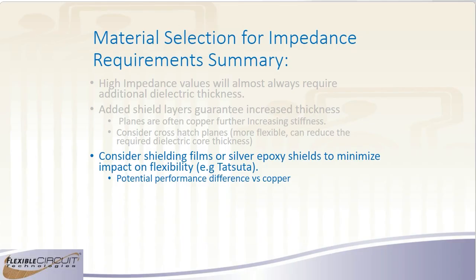And another thing to consider to try and get it more flexible if you do need impedance or isolation is a shielding film. And there's a couple different versions on the market these days. The most common is made by Tatsuta, and it's basically a single laminate that has multiple layers in it that have an anisotropic adhesive and a conductive layer and also an insulating layer. And the entire stack-up is less than a mil thick, and so you can add that to your outer layers. You put holes in your outer covers in your flex that expose traces that you want to connect your shield to below, and so the anisotropic adhesive will make those connections. And you can end up with a much thinner circuit and still get some of the benefits of a full copper shield.